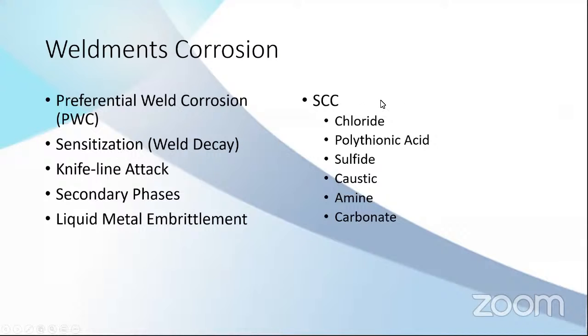So this is predictable and it can be monitored. The second one is SCC, or stress corrosion cracking. This is the worst of all, because normally it cannot be predicted when it will happen, because it's a crack. When a crack happens, it's very easy to lose the pressure containing strength. And these cracks can be caused by many factors.